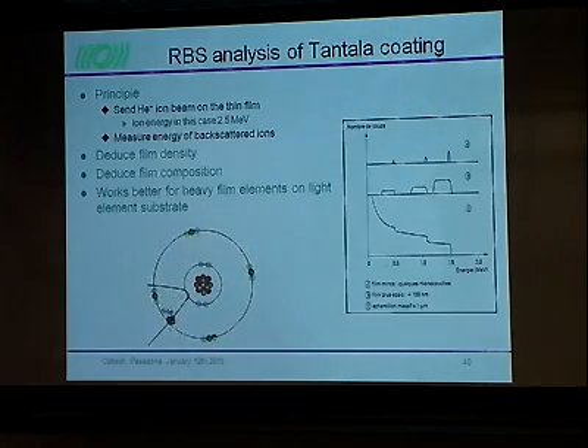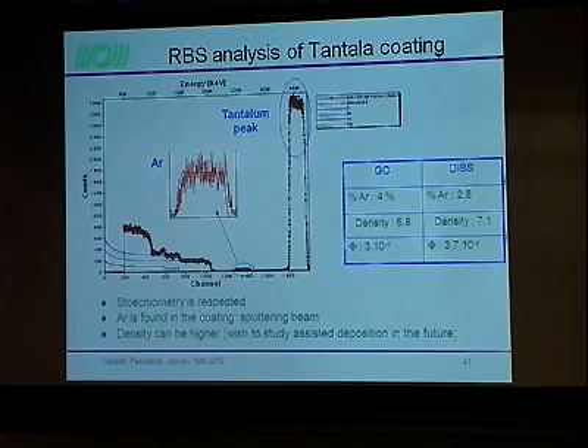We are doing other studies to better understand the structure of this material by using a Rutherford backscattering technique. You send a helium ion beam on the coating, and from the backscatter information you can deduce the density and the composition of the film. This has been used to measure, for example, the amount of argon we have in this coating, and also to measure the density. We have seen density at the level of 7 grams per cubic centimeter. This is slightly lower with respect to what you expect from pure tantalum pentoxide. We believe that this can be improved by using assisted deposition, so another ion beam which assists the deposition and helps making the film more compact. This is something that we want to try in the future.